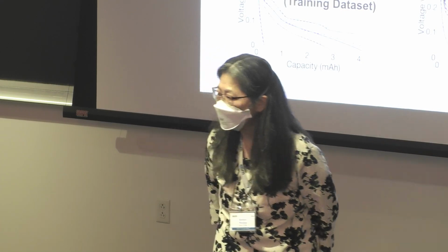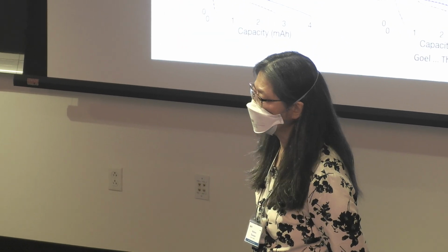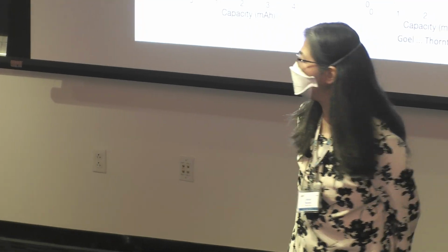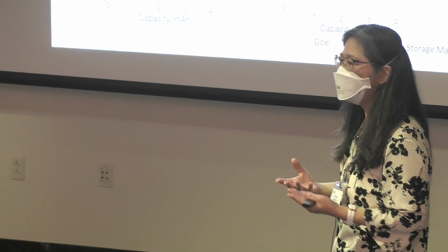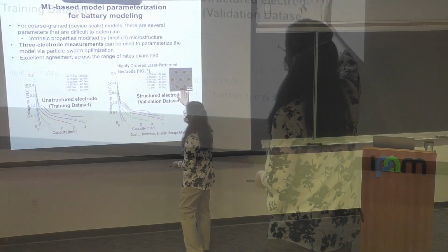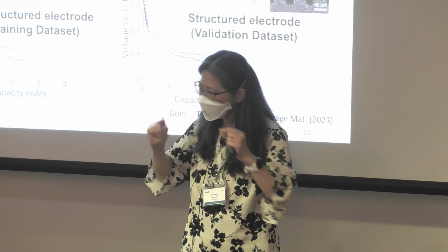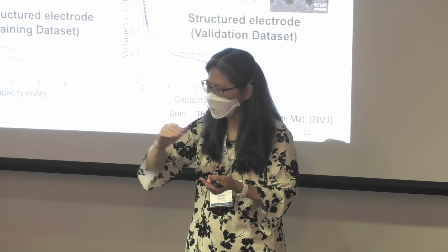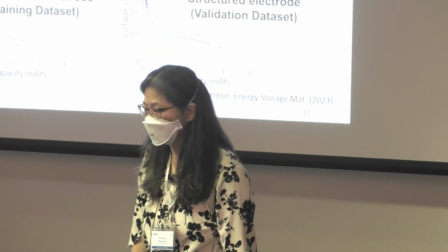Okay, but I would imagine the Butler-Volmer coefficients and things like that. Yeah. So open circuit voltage is one of them. That's quite important. And then actually diffusivity. And then, again, it depends on the system, how you made it. But the diffusivity, at least in the anode, because of the calendering process, you have a platelet-like shape. So the lithium diffusion has to happen in a very tortuous manner. So diffusivity of electrolyte is quite important.